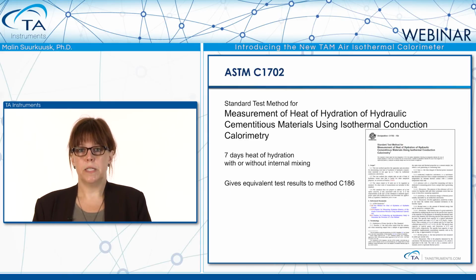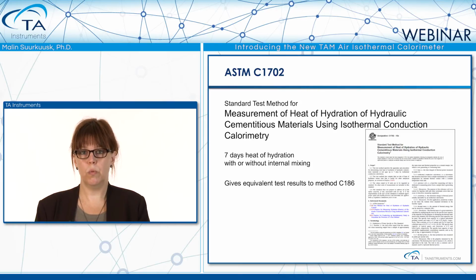There are 2 ASTM standards associated with the cement. We have the C1702, which is a standard test method for the measurement of heat of hydration of hydraulic cementitious material using isothermal conduction calorimetry. And conduction calorimetry is the same as heat flow calorimetry. This method states 7 days measurements for the heat of hydration with or without internal mixing. And this method will give you equivalent results to the solution calorimetry ASTM method C186.